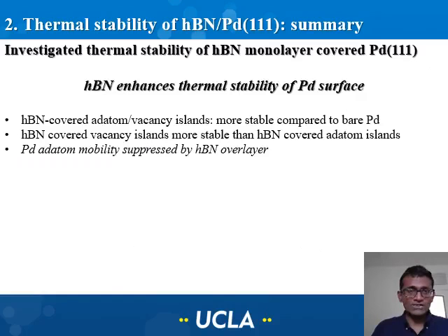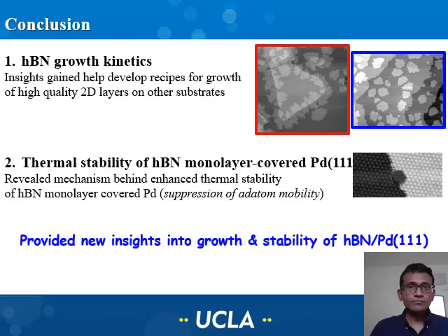I'm going to quickly summarize: having hexagonal boron nitride on palladium enhances its thermal stability, and we have quantified the adatom and vacancy island decay behaviors. And also, finally, in conclusion, we have identified the growth modes that are associated with the growth of carpet-like hexagonal boron nitride on palladium and the role of deposition parameters.